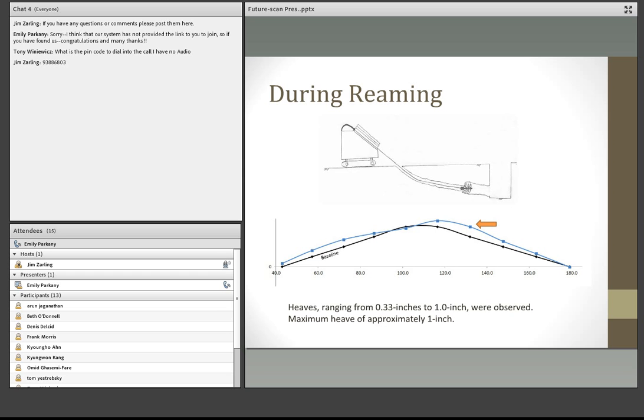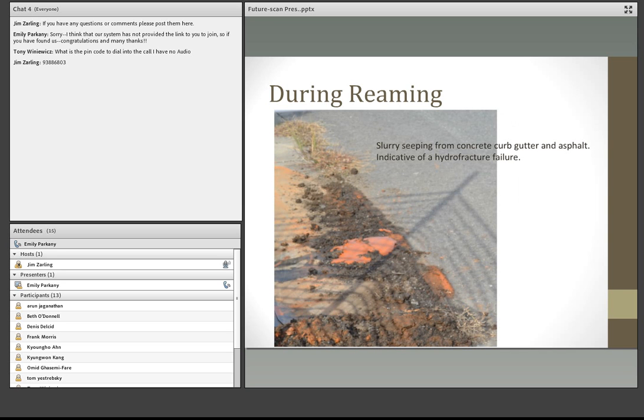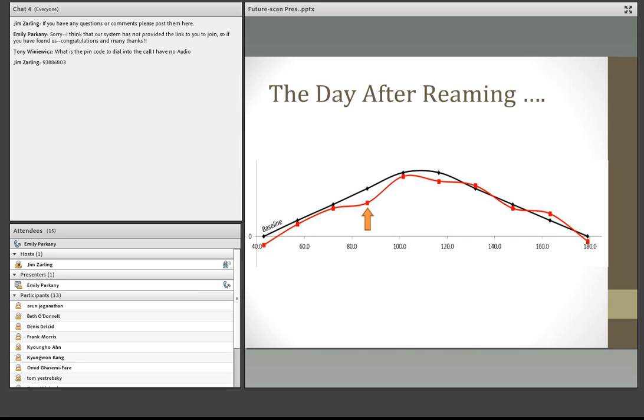So during reaming, we definitely noticed that there was some heaving occurring. The heaving ranged from 0.3 to about an inch. And one of the reasons for this was also that during reaming we noticed that there was some hydrofracture failure. You can see that from the picture here. So we think probably the heave was definitely due to the drilling fluid that was leaking out and seeping from in between the concrete curb, gutter, and the asphalt. The elevations the day after reaming showed some settlement. So you can see definitely there's some settlement here, and in some places settlement was a little bit more than an inch.